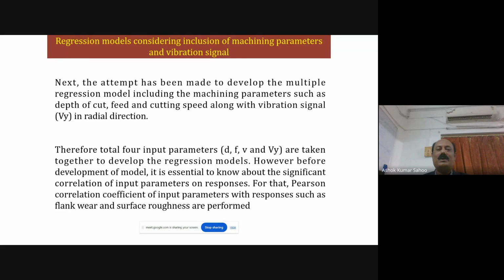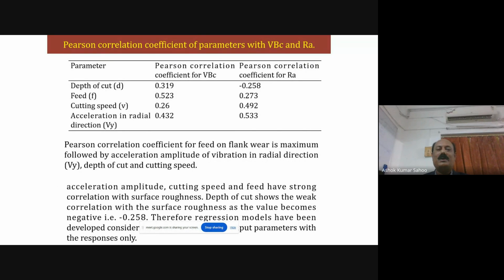For that reason, we analyzed the Pearson correlation coefficient of the input parameters with outputs such as flank wear using the software. It is obtained that for flank wear VBC, the Pearson correlation coefficients are all positive and of higher value. Feed is highest, next comes acceleration amplitude of vibration, then depth of cut and cutting speed. All four are significant because they are all positive values. But for roughness, cutting speed, acceleration amplitude of vibration, and feed are significant, but depth of cut is not significant or correlated because it has a negative value. So depth of cut shows a weak correlation with surface roughness as it becomes negative. Therefore, regression models have been developed considering only the important parameters.